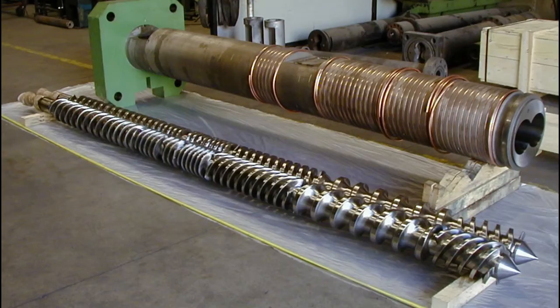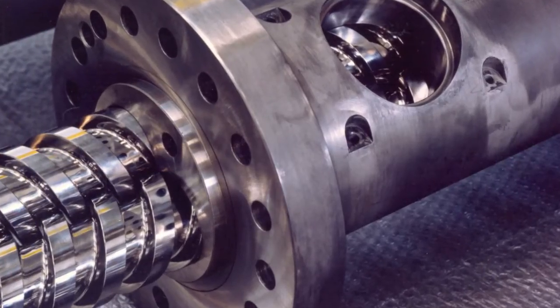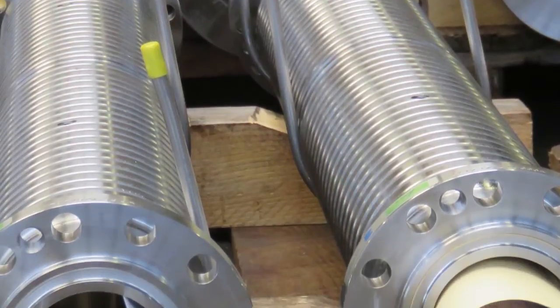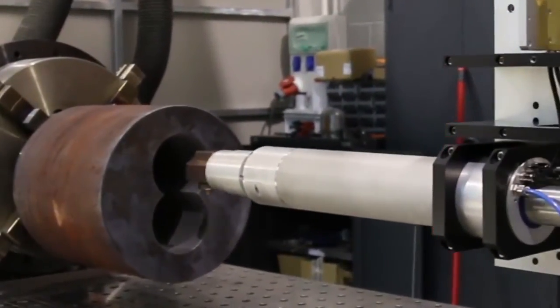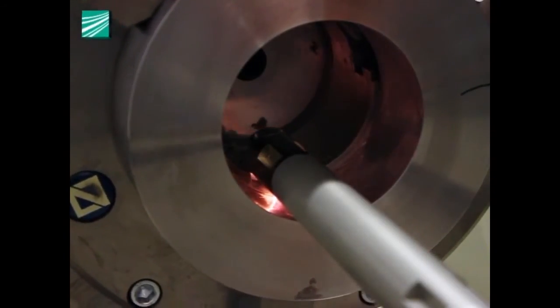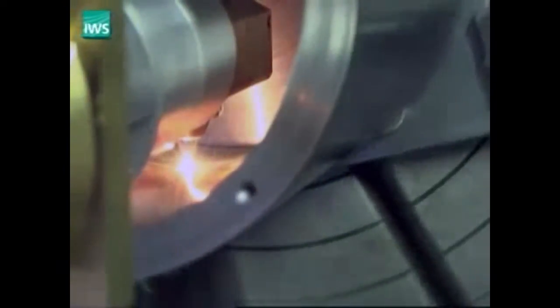Either single or twin screws, cylindrical or conical barrels may exist, depending on production and material requirements. But the degree of equipment wear, especially of barrels, for these techniques represents one of the most concerning issues. It determines the economical feasibility of processing. For this reason, in heavy applications, a hard coating is formed on the inner surface of barrels. Different sections along barrel length are subjected to specific loads in terms of different friction, temperature, chemical attack, and mechanical stress due to the different processing conditions experienced.